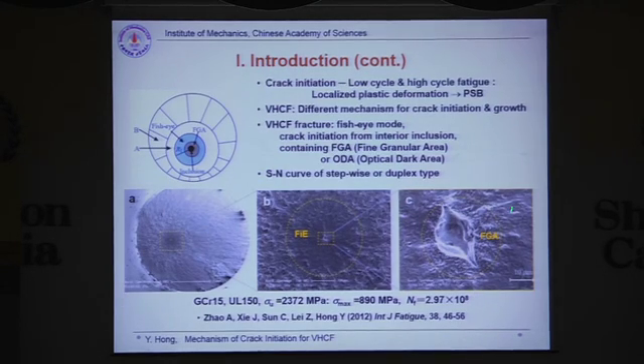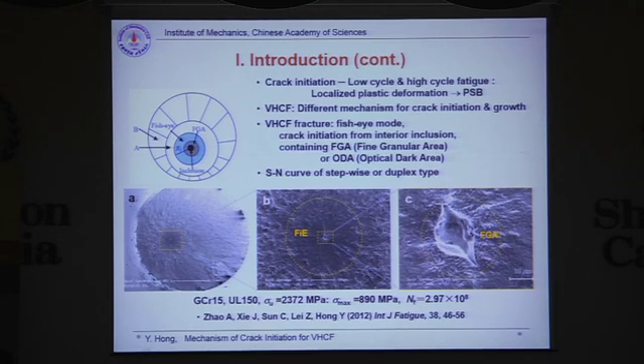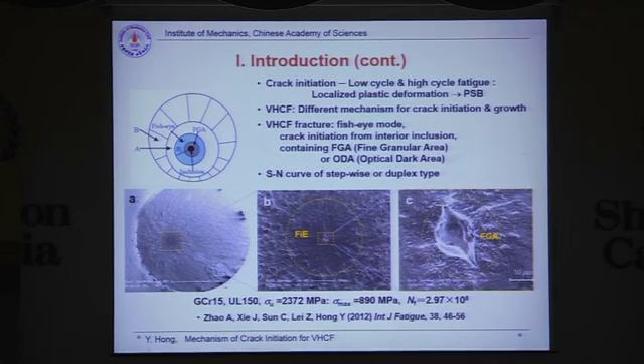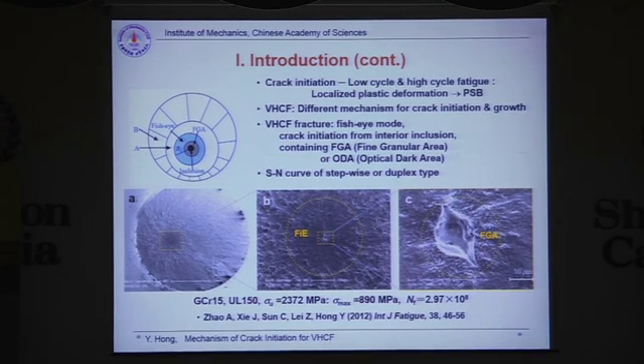This is another example showing what happens in very high cycle fatigue. It shows the crack initiation morphology is a kind of fisheye pattern and also a rough surface of fine granular area. This tells us that for very high cycle fatigue, the mechanism is different from what we know of low cycle and high cycle fatigue. For those, the crack initiation is always from the surface due to some kind of PSB mechanism. But for very high cycle fatigue, it's from the subsurface or interior of the specimen, so the mechanism is quite different.